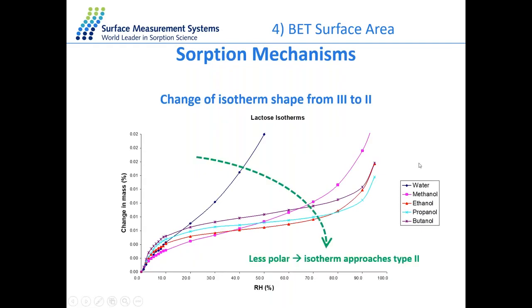So this is having a look at the change of isotherm shape from III to II, looking at the lactose isotherm. And what you can see here, by using water as our probe molecule, we're actually getting a different type 3 isotherm, which is something that we don't necessarily want, and we can't really use in the DVS, because we're looking at different properties of our water interacting with our lactose, causing a bit of change in our material. On the other hand, we're looking at various different alcohols: methanol, ethanol, propanol, butanol, and we're getting a type 2 isotherm. So with this, we can apply our BET equation and calculate a BET surface area, which is more representative of our sample material.